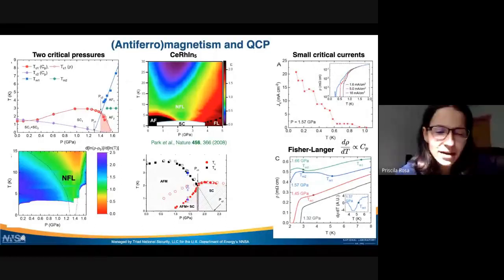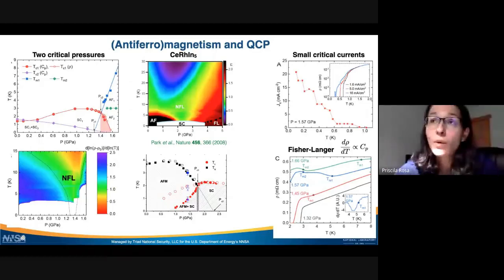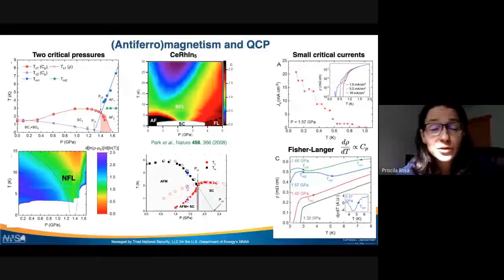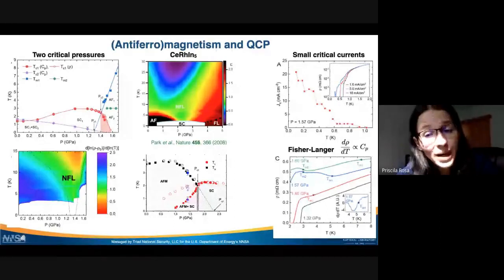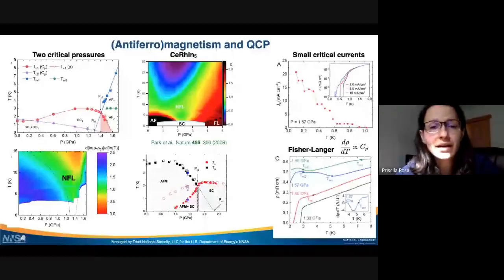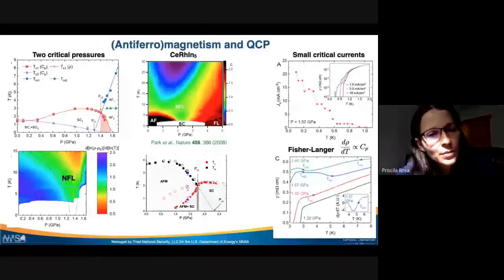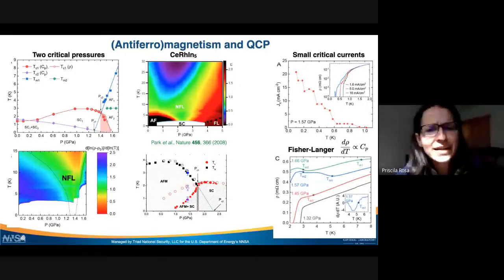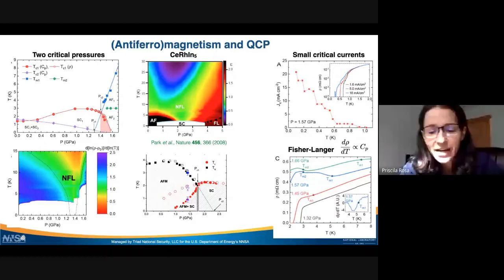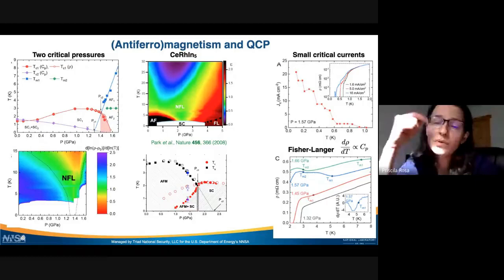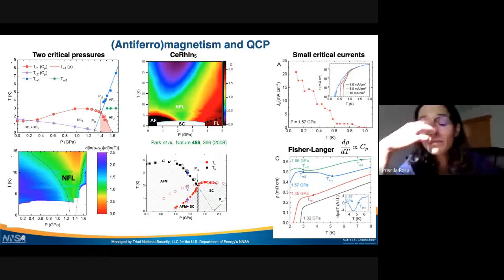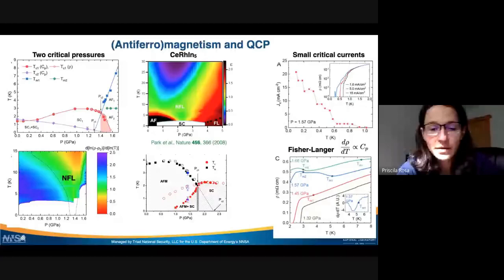And you may ask yourself, why is this important or interesting? Well, it seems to be really inconsistent with the spin triplet behavior at ambient pressure, right? So if we have a spin triplet superconductor, it's often the case that it's close to a ferromagnetic instability. And again, the spins tend to be parallel in that superconducting state. And here we're seeing a rare example where spin triplet superconductivity seems to be nearby an antiferromagnetic quantum critical point. So that's very interesting, and it agrees with our results, as well as many others.